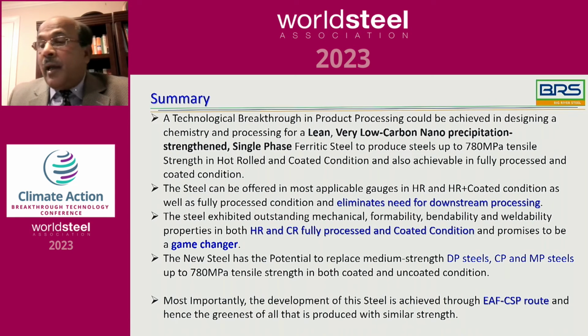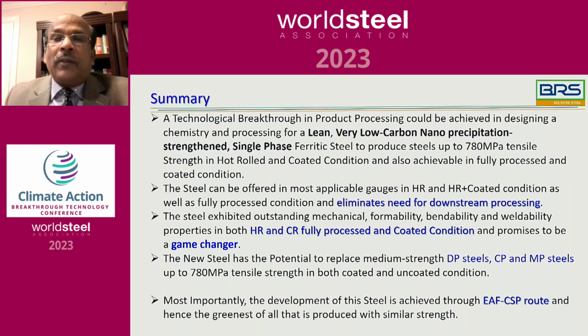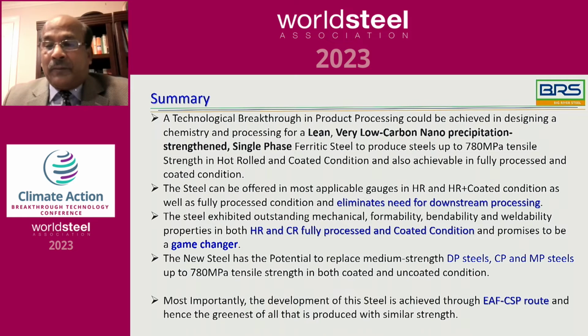The new steel has the potential to replace the medium strength DP steels, CP steels, and MP steels up to a strength level of 780 MPa in tensile strength, both in coated and uncoated conditions. Most importantly, the steel is made through the EAF and CSP route, and hence is the greenest of all the steel produced with similar strength and formability properties.